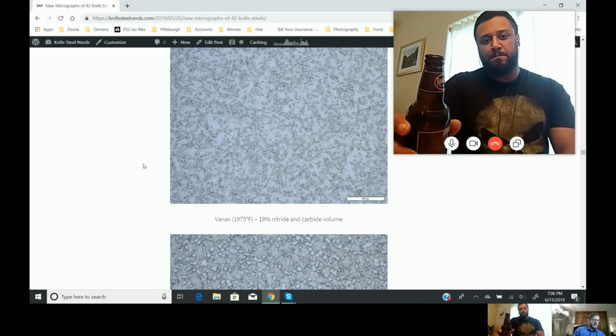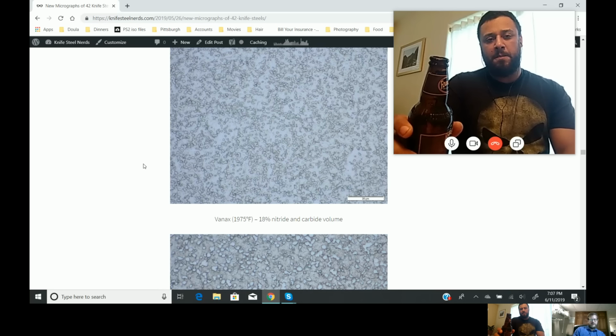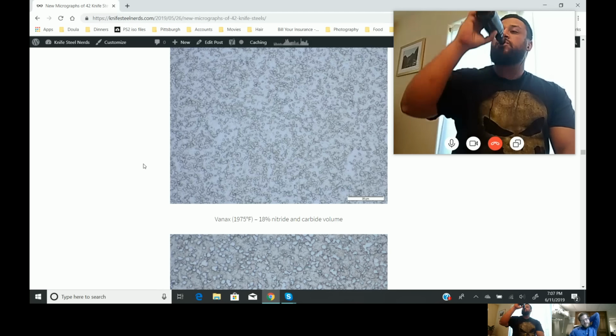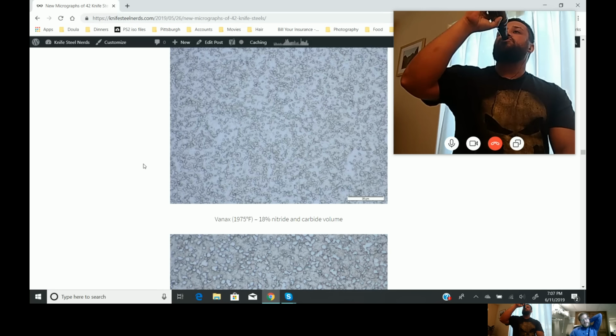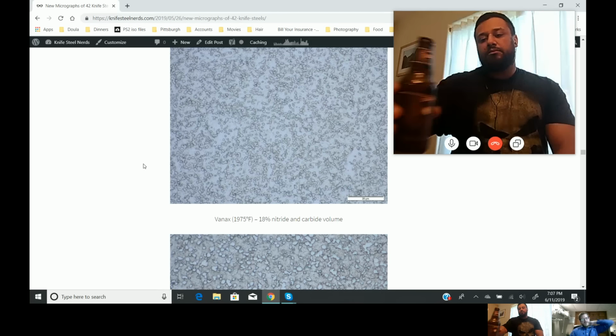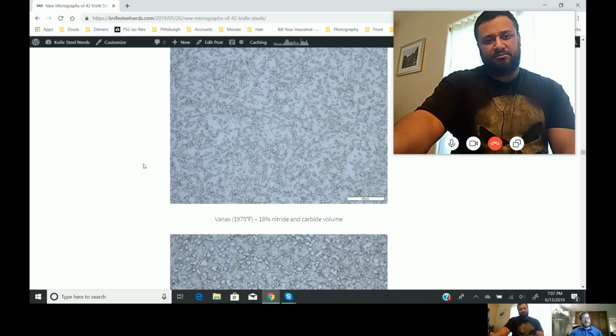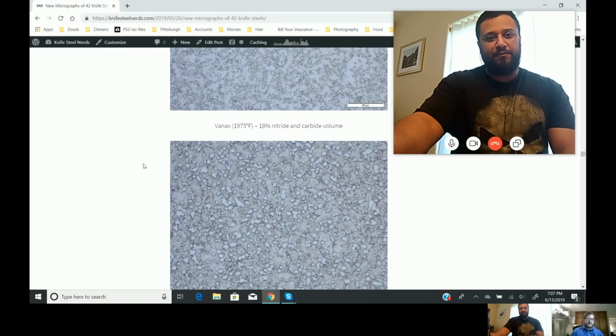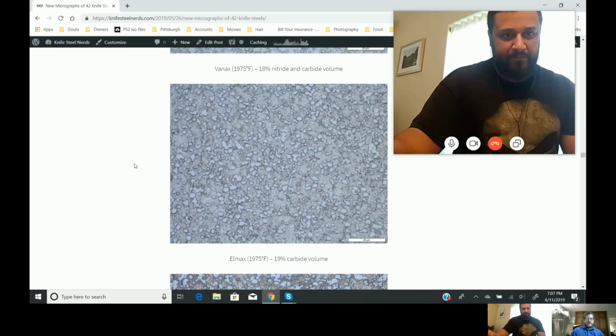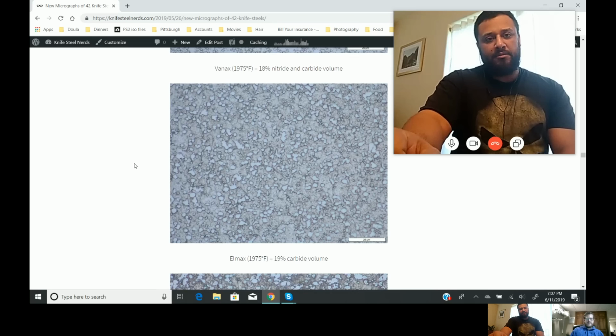Yeah. In automotive sheet steels that I develop at work, we normally get very little carbide. We're not trying to make carbides. But titanium nitrides, we get in really small amounts in some steels intentionally to take care of the nitrogen so it doesn't do other negative things. And those titanium nitrides can be several microns in size. Finer details, man. Fascinating.